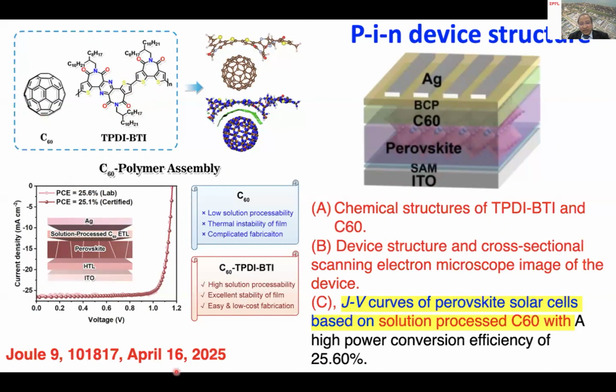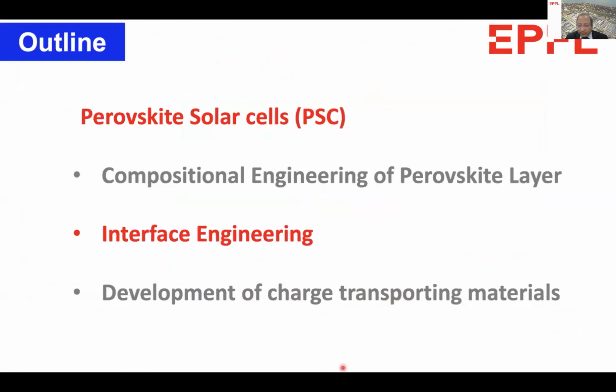This work appeared this year, 2025. What happens is when you deposit by solution processing, you can eliminate the BCP and then you form a very nice PIN configuration. And that gives you 25.6% efficiency. Now we are eliminating the sublimation process and we are reducing this aggregation of the C60 by using the solution processing method. That's the take-home message.